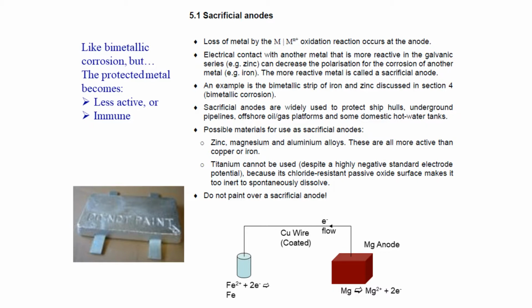What you need in your sacrificial anode is a reactive metal that undergoes continuous active corrosion or dissolution, because it's precisely that process which moves the surface of the two-metal system to a potential that's less corrosive for the protected metal. It's very common to use sacrificial anodes at sea, on oil rigs, on the sides of boats, and sometimes inside domestic hot water tanks.